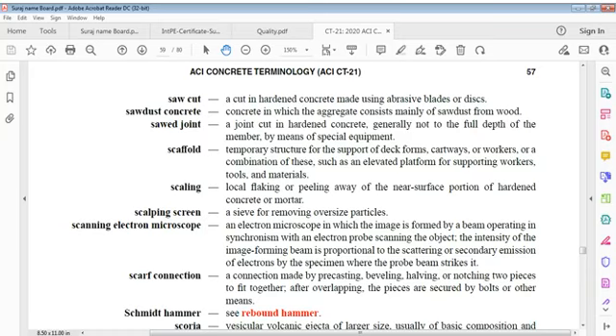This is the definition of lignocellulosic material: it decomposes in the presence of water. When sawdust absorbs water, lignocellulosic components such as carbohydrate, lignin, and cellulose decompose into cement-bound material. This component that decomposes affects the overall strength of concrete. Also, sawdust differs in its physical properties from sand, and the way sand easily mixes with cement differs from the way sawdust mixes. This might also contribute to the variations exhibited by cubes containing 25% to 100% sawdust replacement of sand at 21 and 28 days curing.